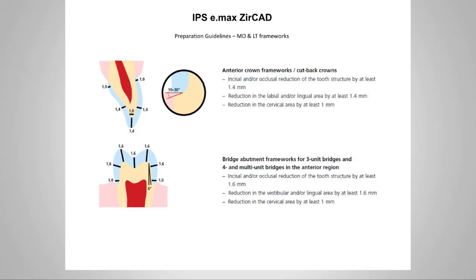If you're using the MO or LT frameworks, this is for cutback. We want at least 1.4, I usually say 1.5 millimeters, on the incisal edge and the lingual concavity areas, and about 1 millimeter at the cervical areas. Once again, this would be like bridge abutment frameworks. You're going to see the same on the posterior, 1.6 at the occluding surfaces, and then around the cervical areas we're looking at least 1 millimeter.